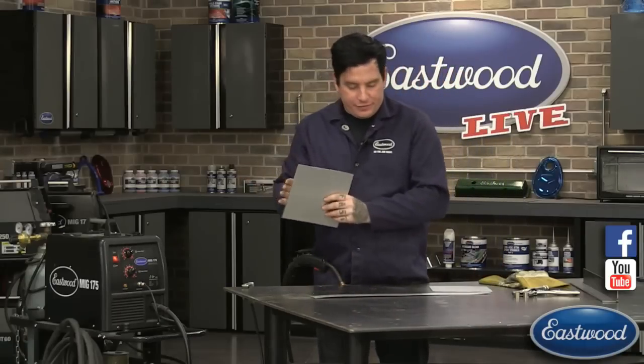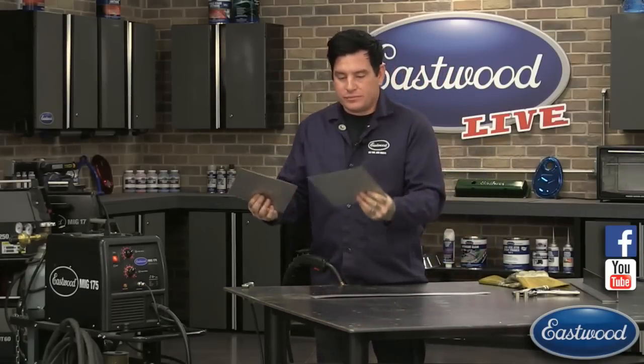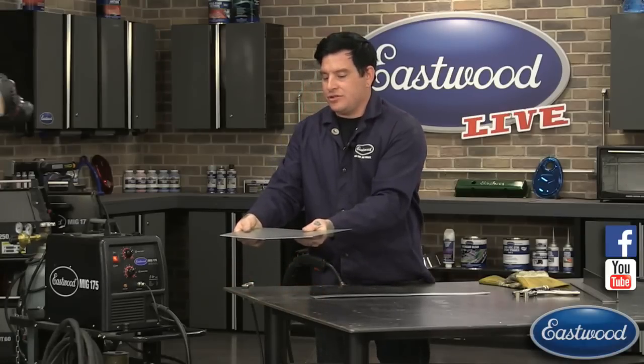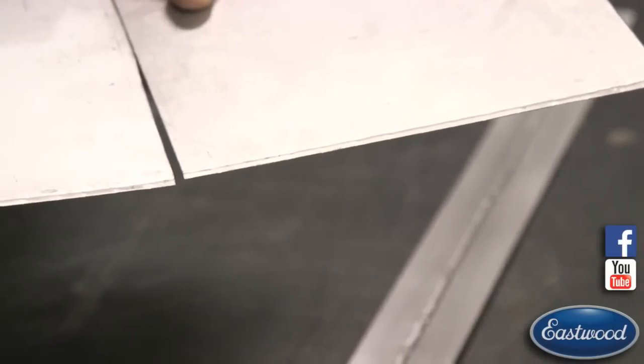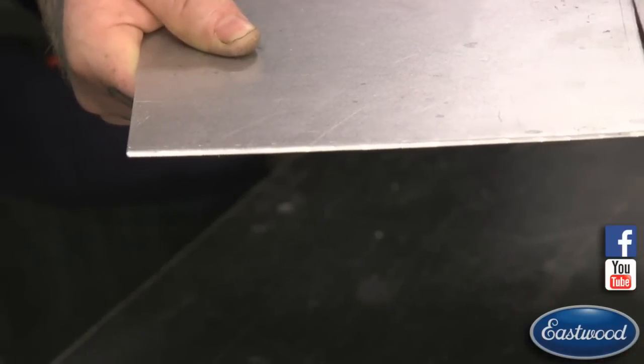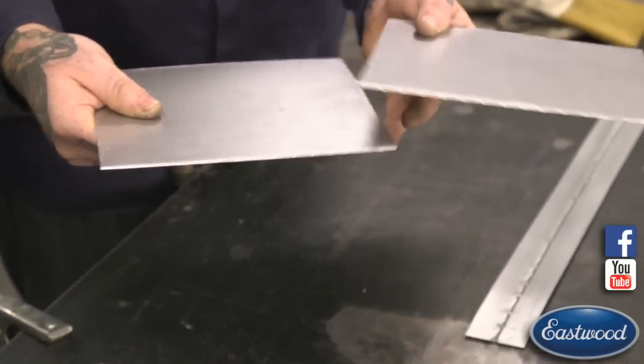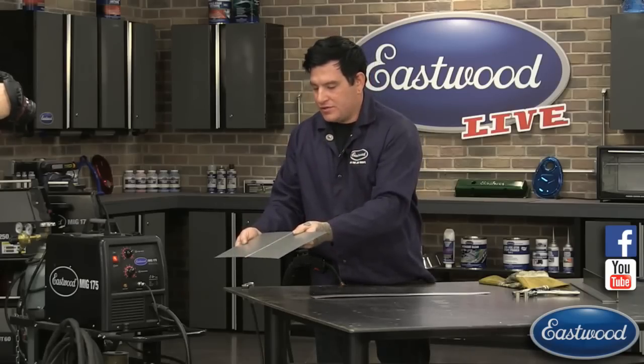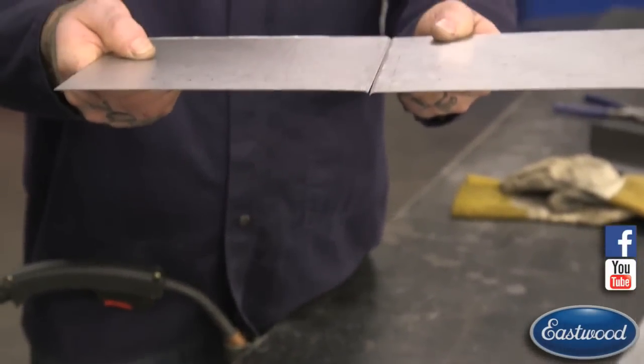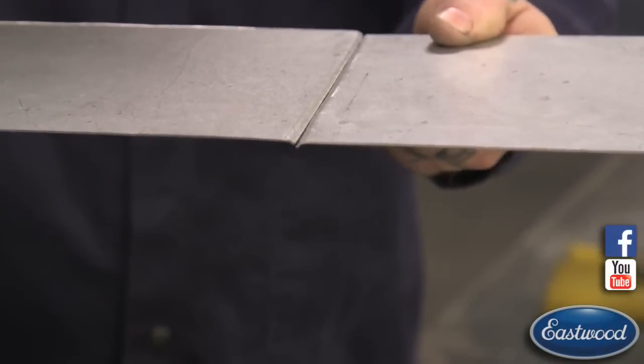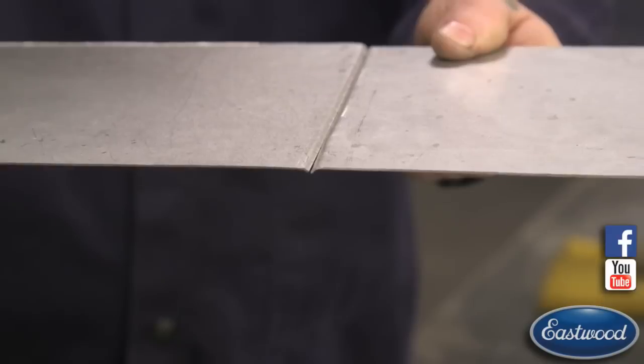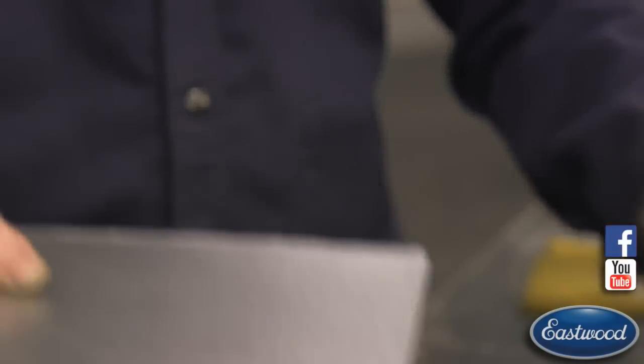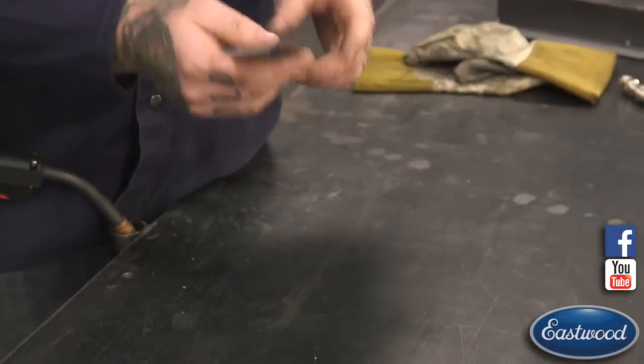So I have two that we did for a sample that aren't tacked together here. So if you can see, I'm just going to try and get a better shot to see the edge of these. So it puts a little tiny bevel on it, not a lot, but just a little rolled edge that leaves an area that you can lay your weld into. And then when we put this together here, like so. Just trying to get this so you guys can see. I'm going to try and hold these. You can see it leaves a little valley that we can weld in, which is pretty cool. Now I have one here that I got set up that we're going to actually do some welds on that you can see.